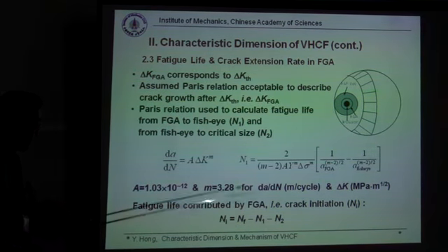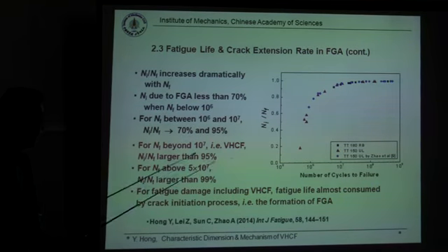So from this simple consideration, we may get the fatigue life contributed by crack initiation in the very high cycle fatigue regime. It's more than 95%.